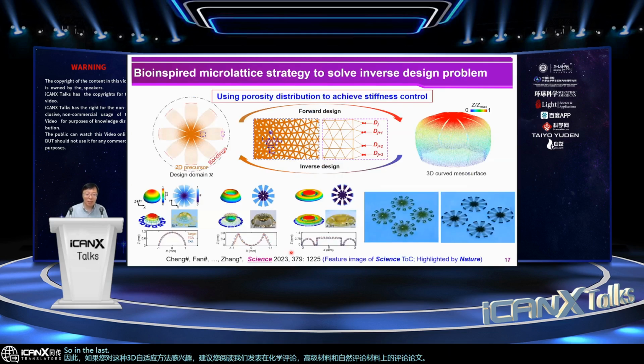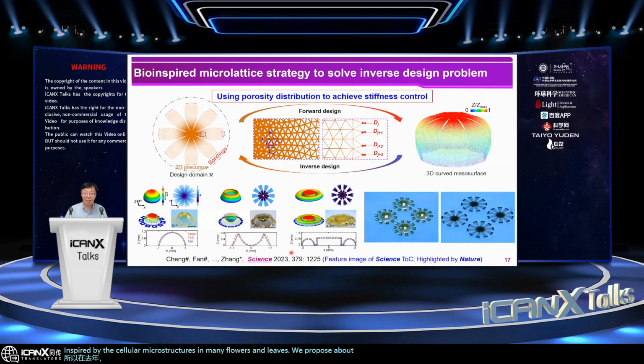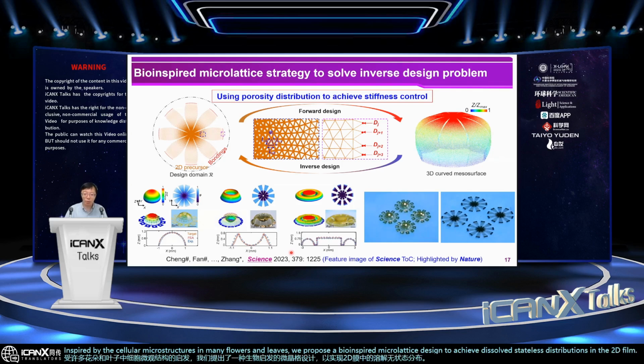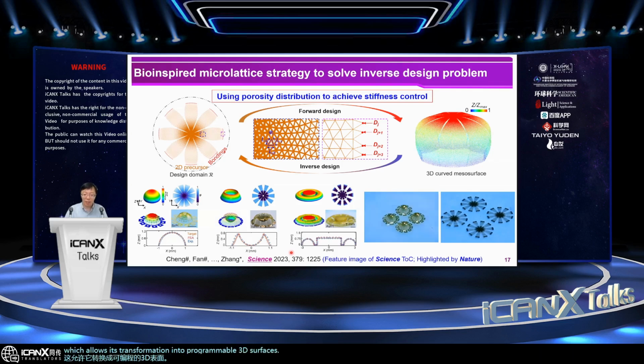So in the last year, inspired by the cellular microstructures in many flowers and leaves, we proposed a bio-inspired microlattice design to achieve desired stiffness distributions in the 2D film, which allows its transformation into programmable 3D surfaces. And based on this microlattice design, it can effectively solve the inverse design problem. That is, for a given 3D curved surface, we can use this method to determine quantitatively the 2D precursor pattern, the porosity distribution, and the loading magnitude.